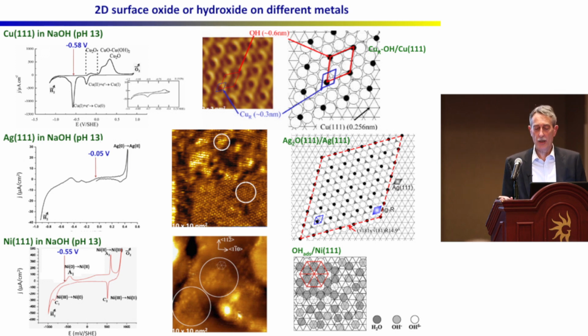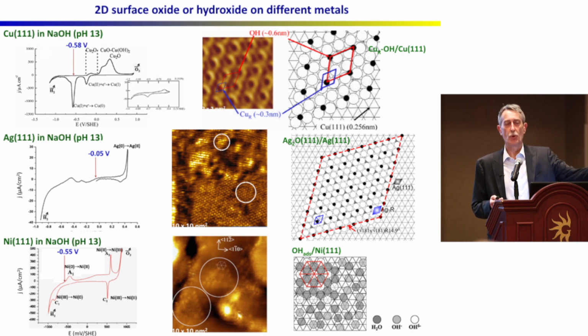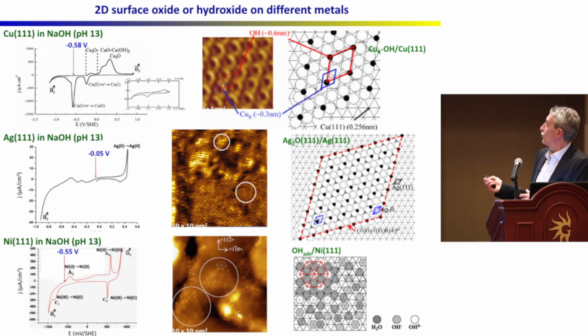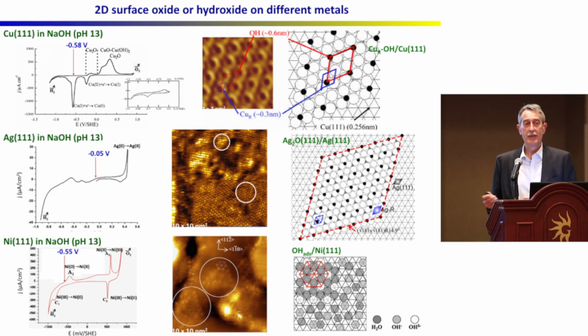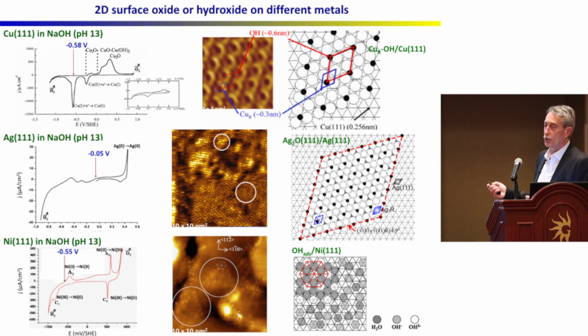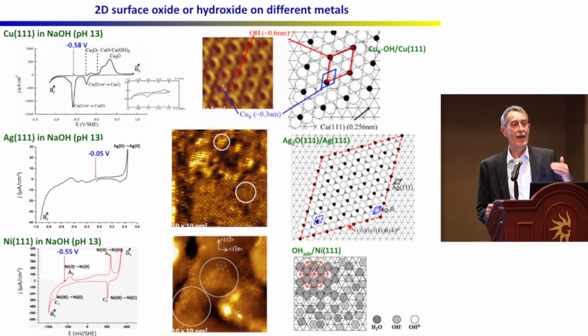So the message here is that if you put a metal surface in water, you get an ordered layer of dissociated water molecules that is very much related with the structure. So it's an epitaxial relationship between this layer and the metal. And actually, this is important to understand passivity because this has exactly the structure of one layer in the oxide that would be formed if you then increase the potential.